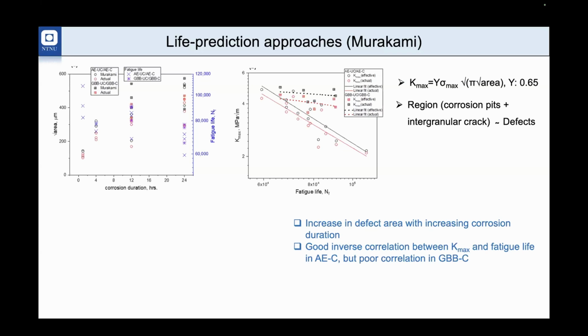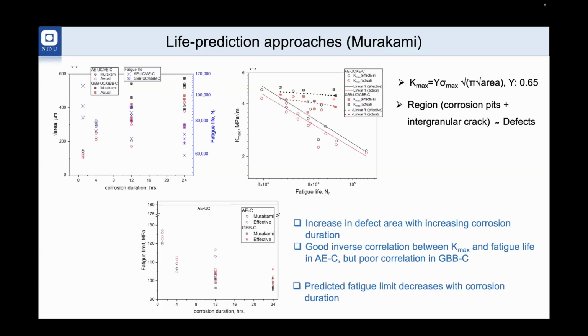And you can see that when you plot Kmax with fatigue life, there is a good inverse correlation in the as-extruded condition, but in the glass bead blasted condition, not. Why not? Because in the glass bead blasted condition, the fatigue life is not entirely dependent on defects. It depends on so many other factors, maybe the work hardening imparted by the impact of those glass beads, or the compressive residual stress. So there may not be a one-to-one correlation between Kmax and the fatigue life.